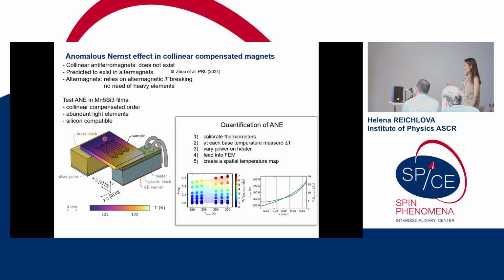One more thing I want to mention is that there is now a search for efficient materials which have high anomalous Nernst coefficients, and typically it relies on heavy elements. There are fantastic works from the environment of Claudia Felser, which, however, very often rely on heavy elements like uranium or ytterbium, which lead to very high anomalous Nernst coefficients. However, in our case the origin of the spin splitting is not related to the spin-orbit interaction. It relies on the altermagnetic splitting by the non-magnetic environment, and therefore the idea is that we don't need heavy elements to have significant anomalous Nernst coefficients.